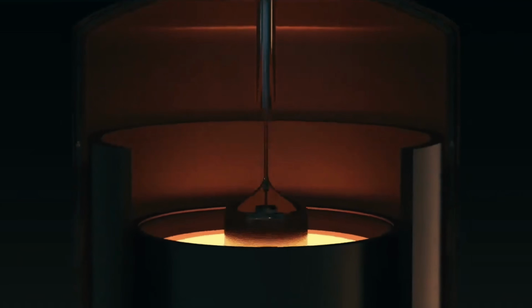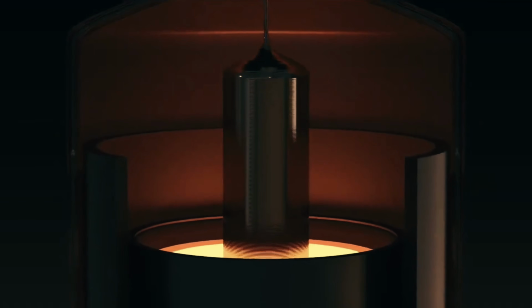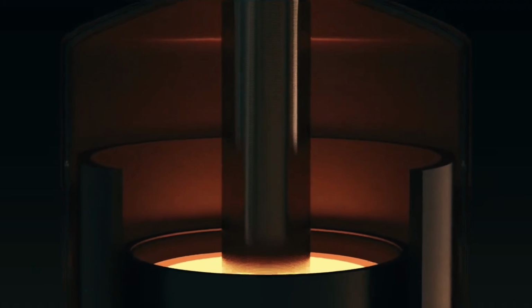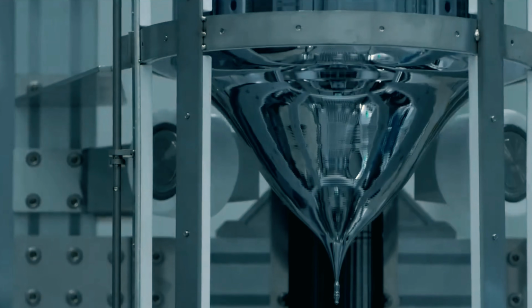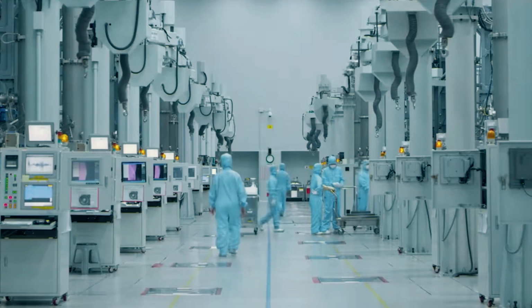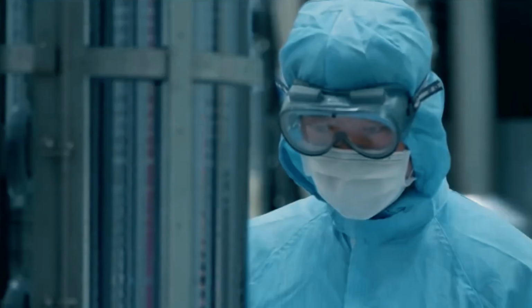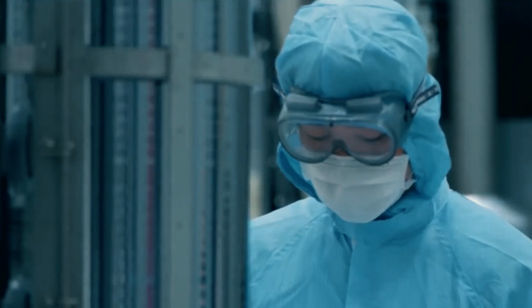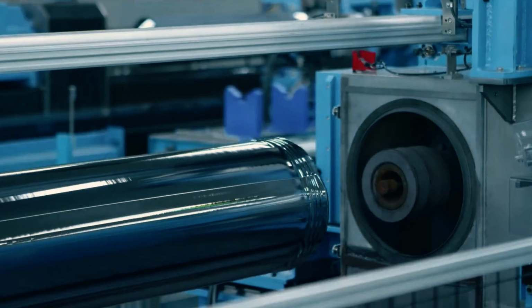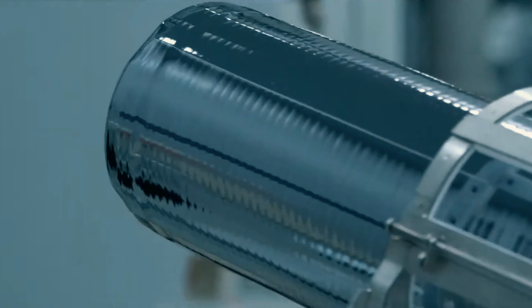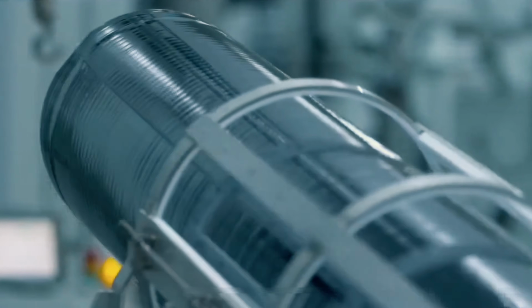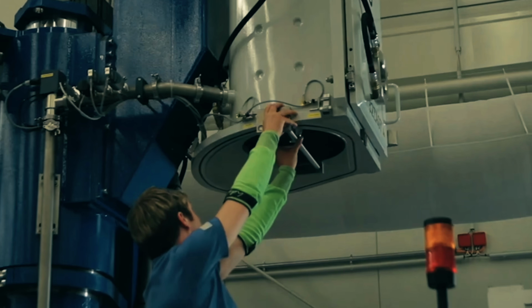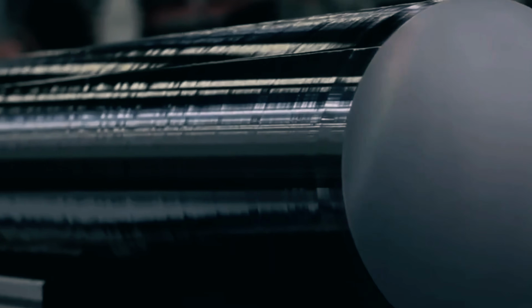Over several days, not minutes, not hours, days, the silicon slowly builds up layer by layer into a thick rod, like stalactites growing in a cave, except engineered, monitored, and controlled down to the smallest fraction of a degree. This method produces what's called polysilicon, and by the time it's done, the silicon is 99.9999999% pure. That's 9 nines.